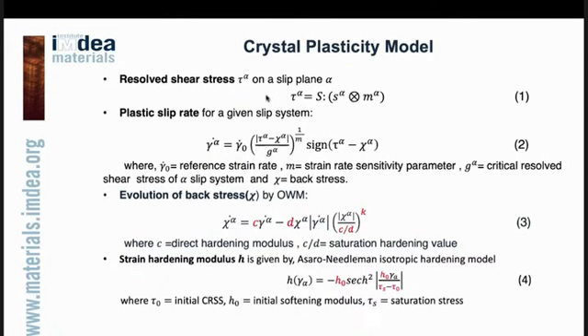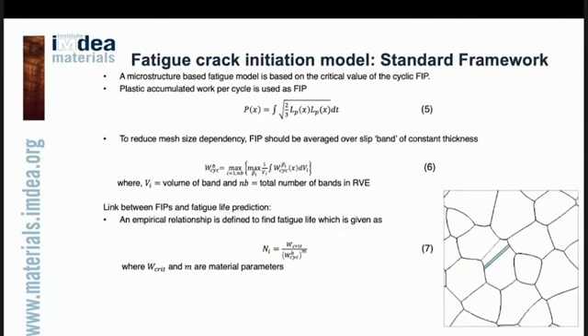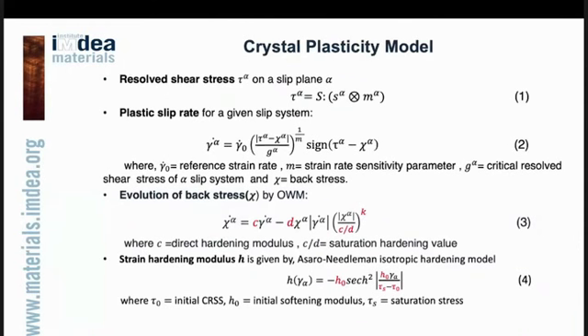The crystal plasticity model is the cyclic one, where equation one shows the resolved shear stress on any slip plane, and the plastic slip system now includes the evolution of back stress, which is given in equation 3. Finally, the strain hardening modulus is given by the Asaro-Needleman isotropic hardening. These are the rate parameters that we need to find using the inverse optimization approach, which we will discuss further.